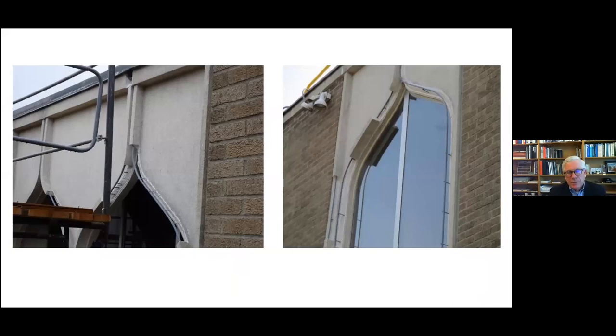The double reverse curves of the ribs were a little bit more challenging because of the shapes and the difficulty of access and placement because of the varying degrees of how you would place the formwork. But the basic techniques followed the same: chipping behind reinforcing bars, cleaning the repair areas, and other examples of good concrete practice.